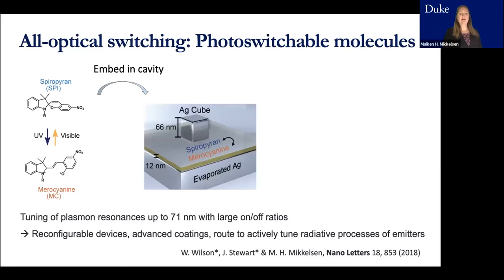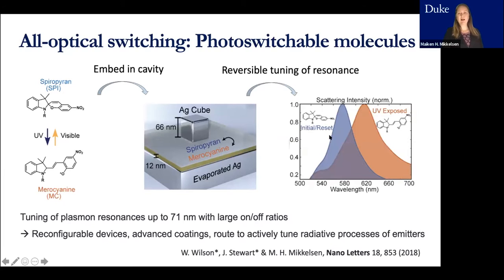And when we embed that in these nanogap structures, it allows us to do a reversible tuning of the plasmon resonance, because we're changing the index of refraction of this gap, and there's also some resonant coupling. It's complicating things a little bit. But we can tune the plasmon resonance up to about 70 nanometers with large on-off ratios here. So you can think about utilizing this potentially for reconfigurable devices, advanced coatings, and also be a route to actively tune radiative processes of emitters.